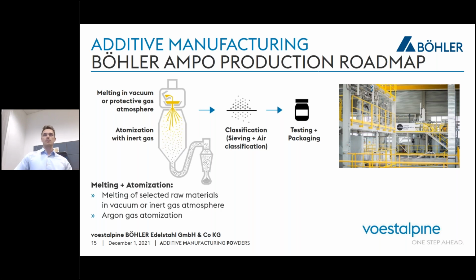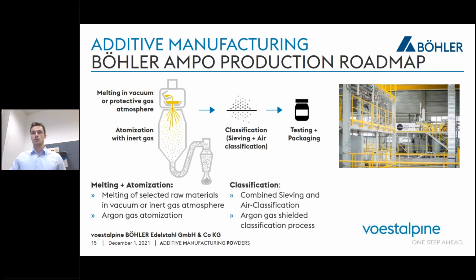And to give you a more detailed overview about our atomization process, we're here in the melting and atomization step. So basically, you melt your metal in vacuum, and then it gets atomized with an inert gas. We use argon gas for this. After that, we make sure for highest quality. To achieve highest quality, we have a sieving and air classification step, which is also done under argon gas. So you have the protective gas as well, and also it gets packed under argon gas.